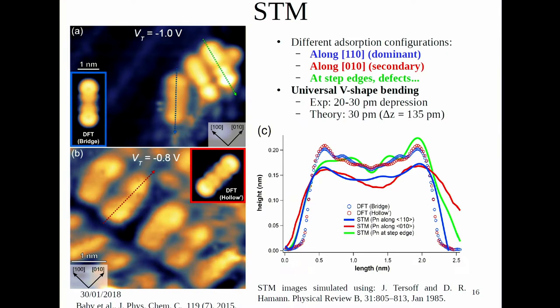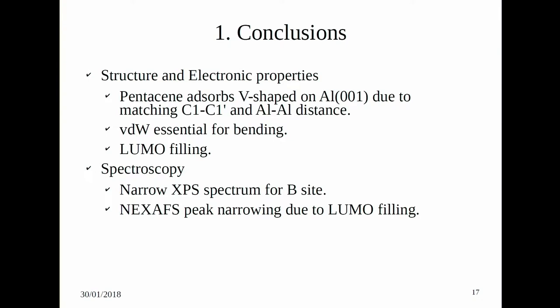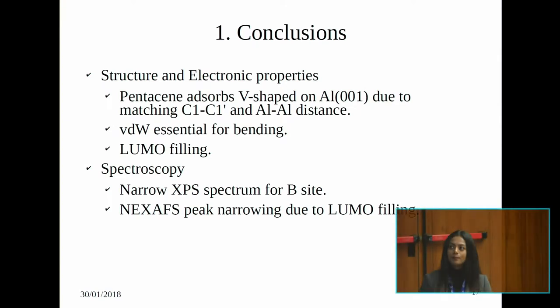The simulated STM for the bridge site corresponds to the experimental image with very good agreement. Looking at the line profile, the V-shape contribution is also seen in the experiment. Concluding this first part: pentacene adsorbs in a V-shape, the LUMO is filled, and this results in narrowing of the NEXAFS peak.